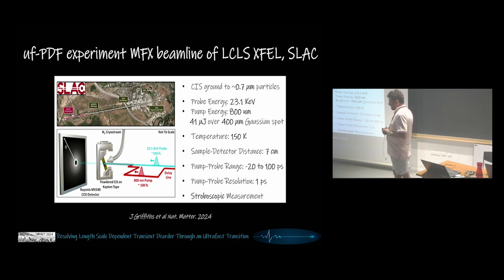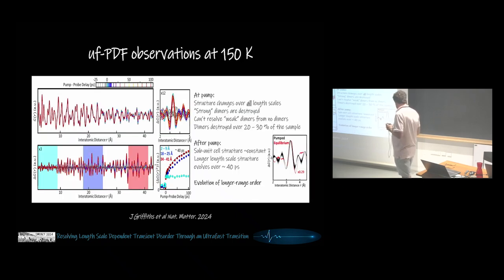I'm just going to say that we covered a regime between -20 to 100 picoseconds delay time with a resolution of 1 picosecond. And unfortunately, we did not get any data in the sub-picosecond regime, which turns out to be, on some level, critical. But there is no limiting factor to not be able to do that. So here are the PDFs that are color-coded and plotted on top of each other. It's not really very important that you can see specific profiles, but what is important is that stuff is happening as a function of delay time.